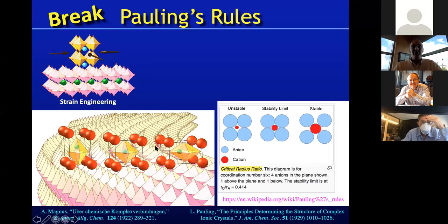If I was at a particular material where in bulk it just satisfied the stability limit, I could think of what happens when I use this strain engineering trick of providing these atoms that I'm going to rain down on the substrate with a substrate that's slightly larger in lattice constant. So that's what's shown here on the right. And if I think of following that existing template of the substrate, it means that this coordination polyhedron, this octahedron of the ruthenium, is going to get stretched in the plane. And when it gets stretched, I'm going to have the condition which Pauling would call unstable, where I no longer satisfy the stability criteria for this radius ratio between the ruthenium and the surrounding oxygen. This ruthenium, if you will, can rattle around inside of its cage.